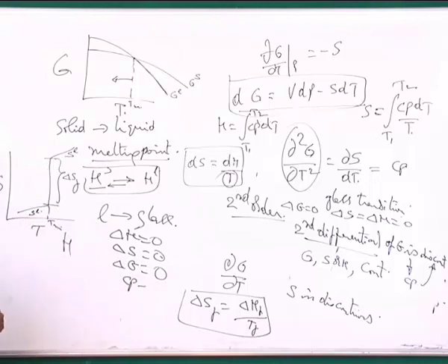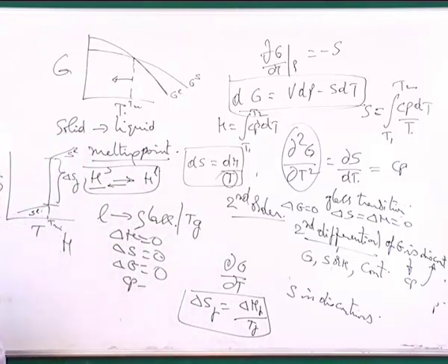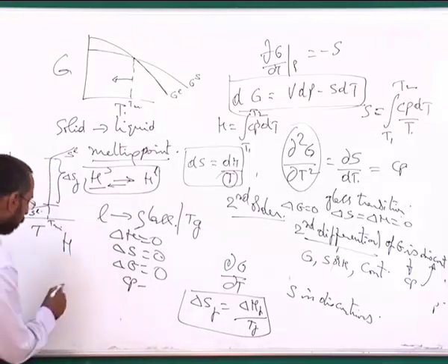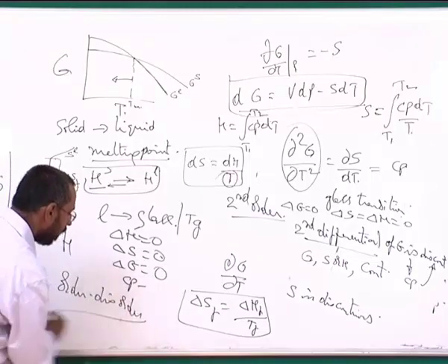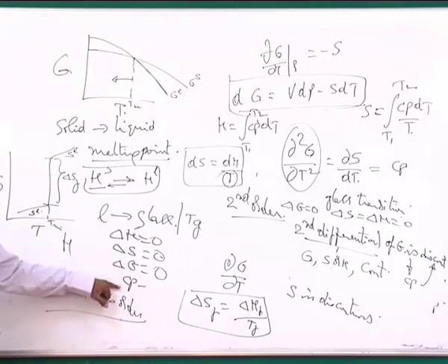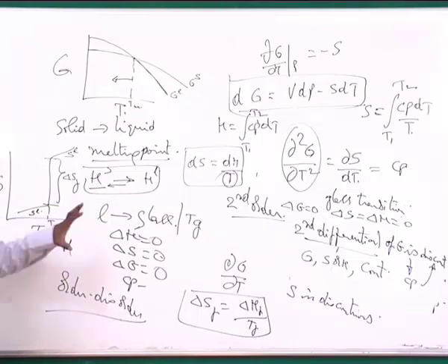This transition happens at what is called the glass transition temperature, Tg. At the glass transition temperature, you will see that the Cp is discontinuous. And this is only one type of transformation. The other type is order disorder transitions. There are quite a number of order disorder transitions which are second order transitions, where the Cp at the transformation temperature is discontinuous, whereas the rest of the things are all continuous. People generally observe this.